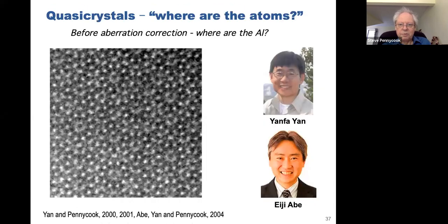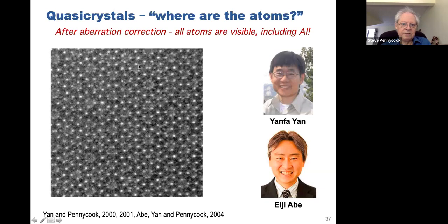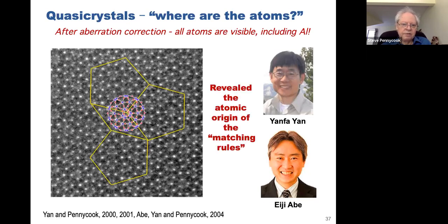Well, some of the exciting things we were able to look at then, we had Yanfa and Eiji come as postdocs and fellows. Before aberration correction, you could sort of see the Penrose tiling pattern here, but not quite see all the atoms. Now let's just turn on the aberration corrector, and all of a sudden these inner rings are nicely resolved, and we can see the structure. Look at this one here. You can see it's twofold symmetric, not 5 or 10-fold symmetric. We could get the structure, and we could see the origin of the matching rules, the origin of the quasi-crystalline